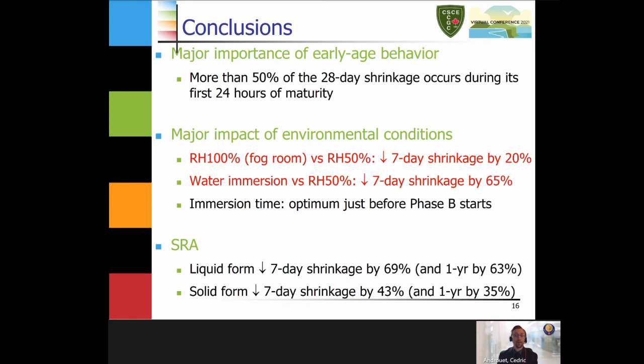And for the SRA, we've seen that when it's supplied in a liquid form and added after water and admixtures, it helps in reducing the shrinkage by almost 70% at 7 days, while when we add the same materials in a solid form, it helps in reducing the shrinkage by a little bit more than 40%.